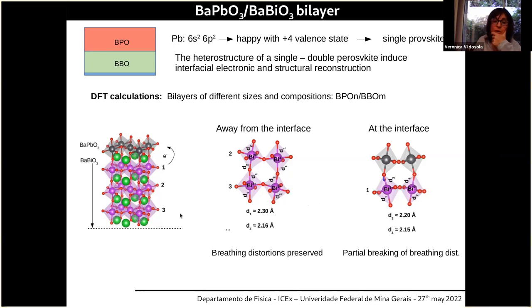From the structural point of view, we observe the breathing distortions. Here you see the bond lengths around the bismuth 3+ and the bond lengths around the bismuth 5+. The structural distortions remain the same as in bulk, far away from the interface, in fact even in layers 2 and 3. But at the interface there was some partial breaking of this breathing distortion, where the bond length between bismuth 3+ and the oxygen decreases, and the other one stays more or less the same. But the distortion between these bond lengths was decreased.